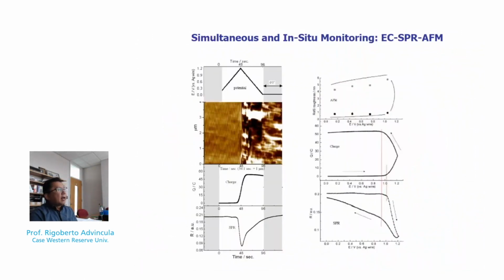So the result is this. We actually have 3 graphs that can be plotted as a function of time. So we can monitor the potential. So as we oxidize, reduce, we can then do the AFM imaging in one line. So it's very important to say that this was done in one line to preserve the time frequency. You can see here the shift in morphology as you go from 0 to 1.2 volts. So that shift in the morphology is actually quite interesting in that it exactly relates to when you shift from an oxidized to a reduced mode or a negative potential.